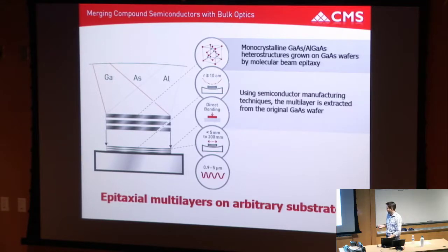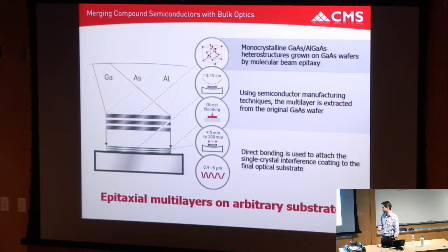We then leverage traditional microfabrication techniques, lithography, etching, both chemical or wet etching or dry etching, to define the lateral coating area. And then I think the one twist we do, but it's becoming more of a routine microfabrication process, is we then direct bond these layers onto the final optic. And I'll point out the details, the key advancements that we came up with in the course of the talk. But in the end, through this nice merger of these two fields, you end up with these epitaxial or single crystal multilayers on effectively arbitrary substrates. And for us, one big advancement was the ability to directly bond these structures onto curved surfaces, which is required for a stable optical resonator.